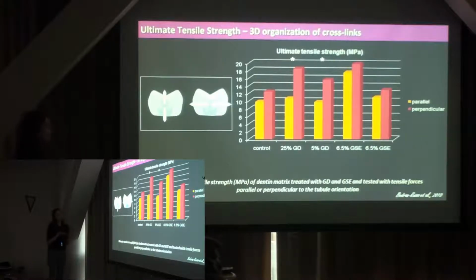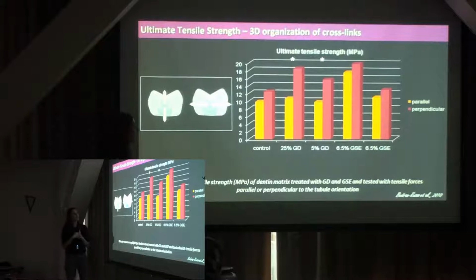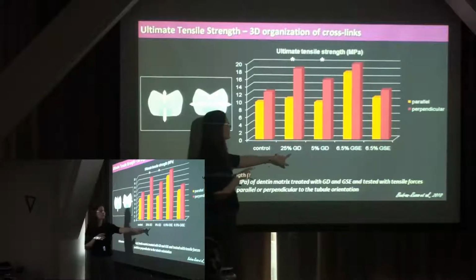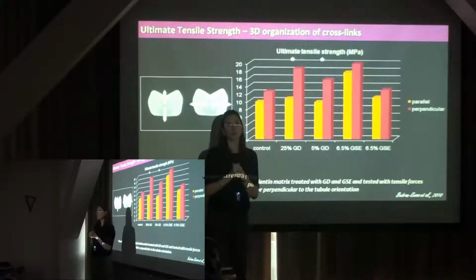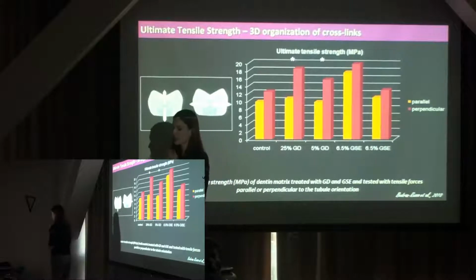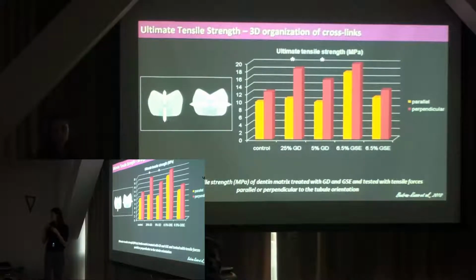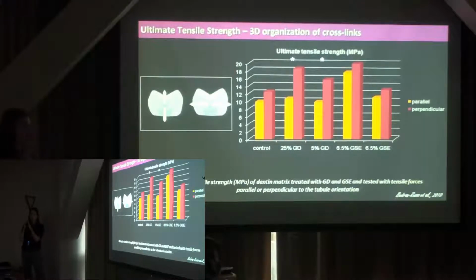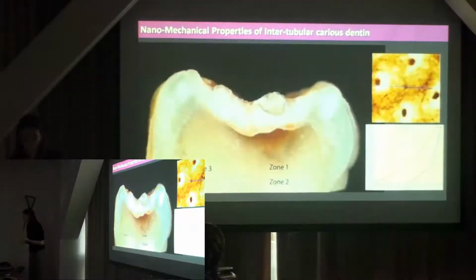So this was an interesting finding for us because when we tested at ultimate tensile strength, we would never get a positive response from glutaraldehyde, even though we could see that the matrix was stiffer. This is very important for us in the tooth because of the three-dimensional ability to restore it. So if you're restoring one side versus the other, you may get different results.